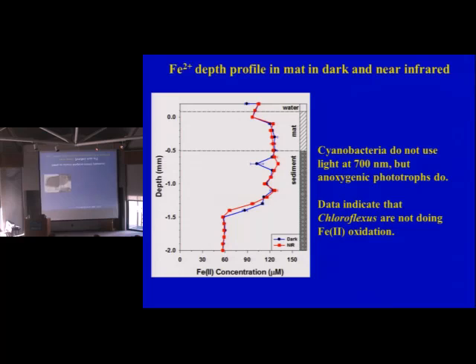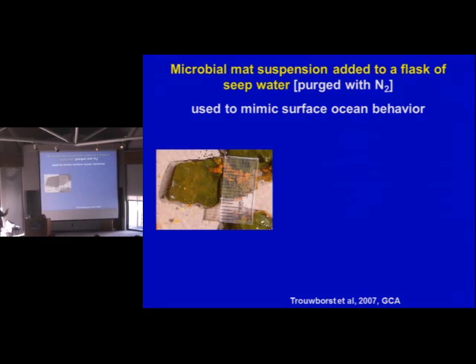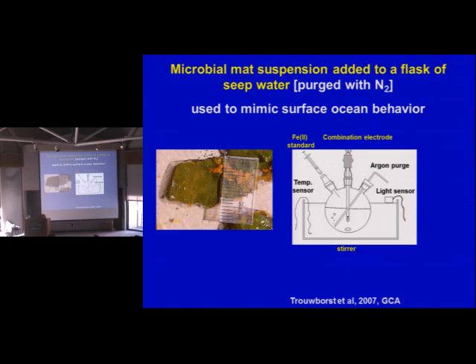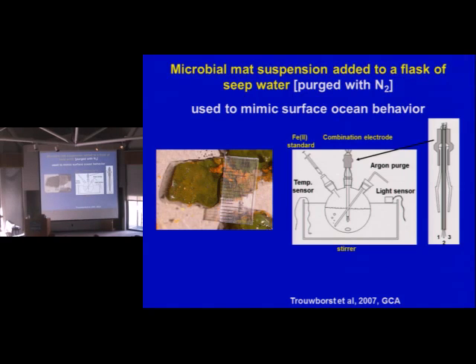ferrophototrophs. So I'm an oceanographer. We decided to do this one. You'll love this. We did this in the parking lot. So we took the mat, and what we did was we threw it into a little round bottom cylinder. We made an electrode which had all 3 electrodes in here. We had a temperature sensor here with a water bath. We injected the iron 2. We had an argon purge as we needed. We had a light sensor. And so we were going to mimic it like this was an ocean. Can we mimic it like it's an ocean?